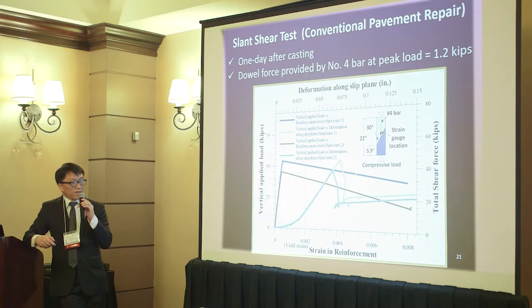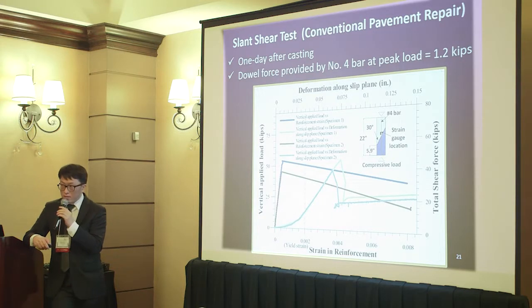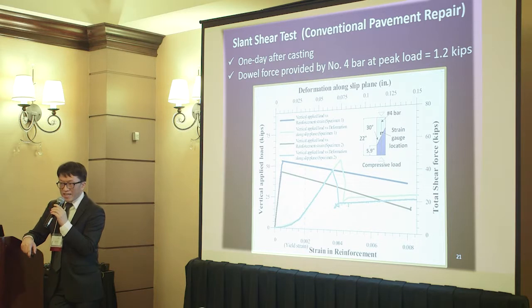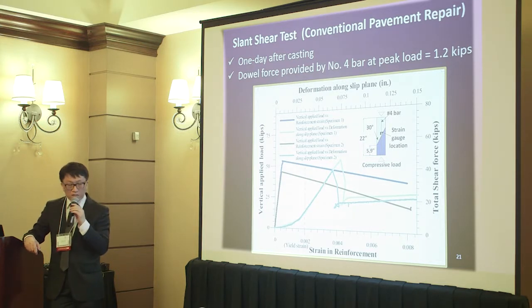There are 2 specimens here, and they have similar performance. This is the applied loading versus the deformation along the shear plane, and this graph shows the strain gauge data on the dowel bar. You can see that before the peak force, the strain in the reinforcement is extremely small. If we back calculate using the strain we measured, we found that the force taken by the reinforcing bar is only 1.2 kips, while the peak force is about 55 kips. This tells us that the dowel bar doesn't actually help much to resist the force. It only acts after the slip occurs. So most of the resistance comes from the concrete itself, not the dowel bar.